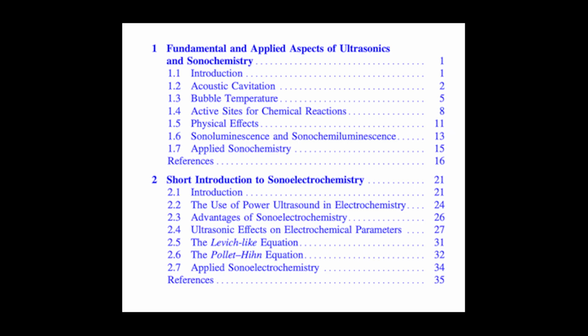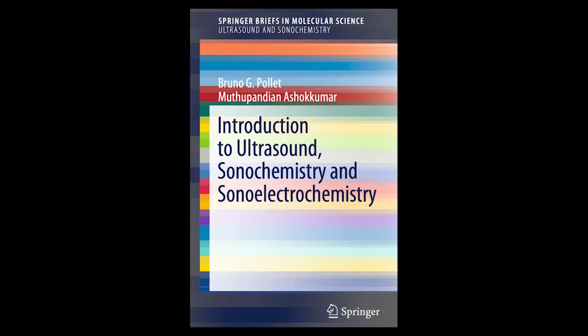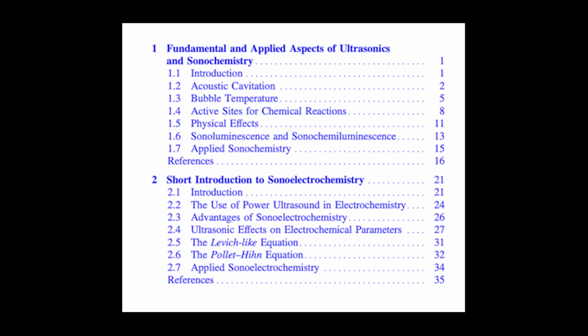That's when things get dramatic. At resonance, the bubble absorbs energy from the sound field incredibly efficiently. Its pulsations become huge, really violent oscillations. It gets so big on the expansion phase that it can't effectively push all that accumulated gas back out during the compression phase. It overshoots, it can't keep up, and the incoming compression wave from the ultrasound just slams into it. This leads to an incredibly rapid, uncontrolled collapse — the violent implosion.